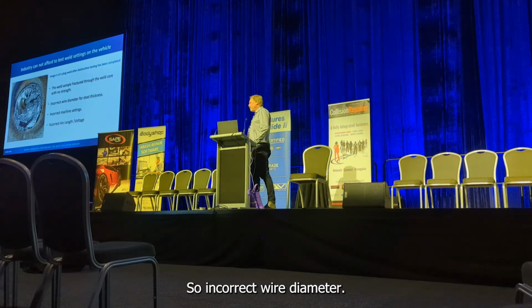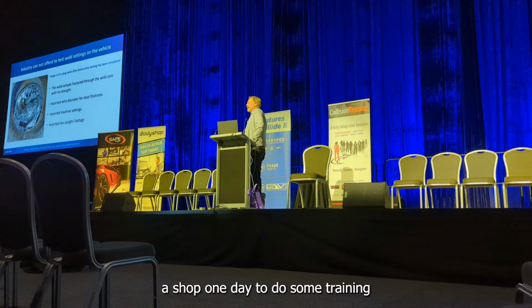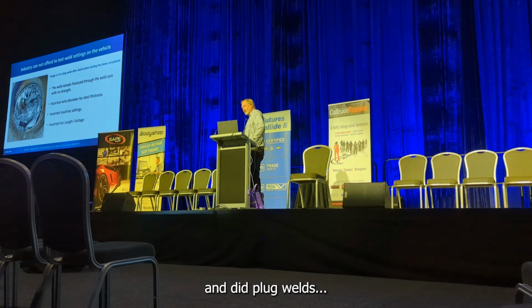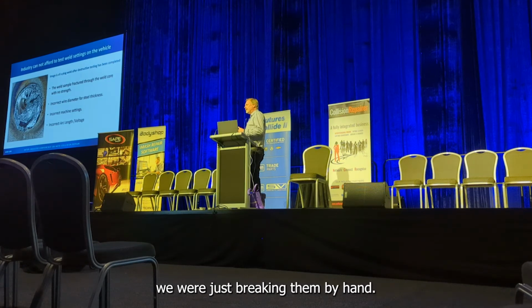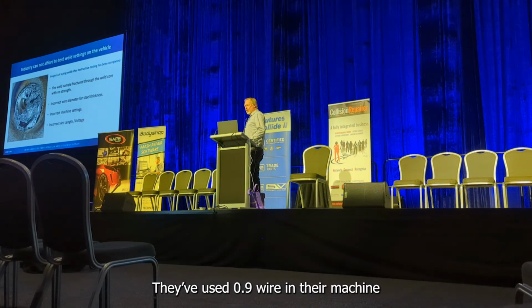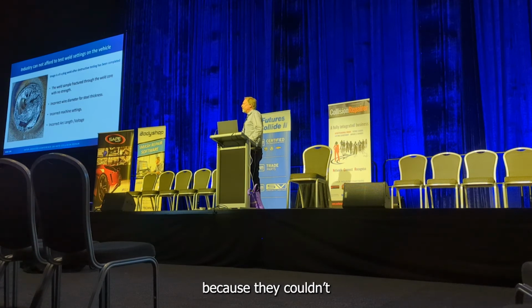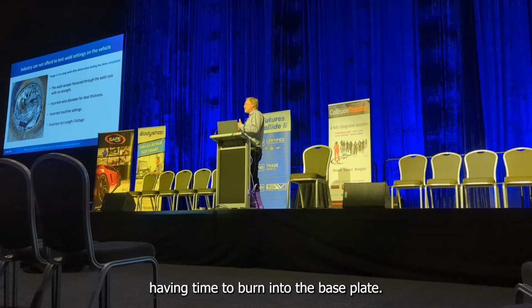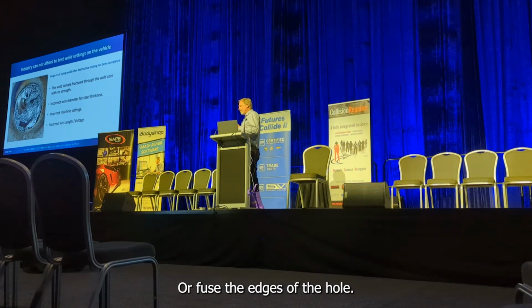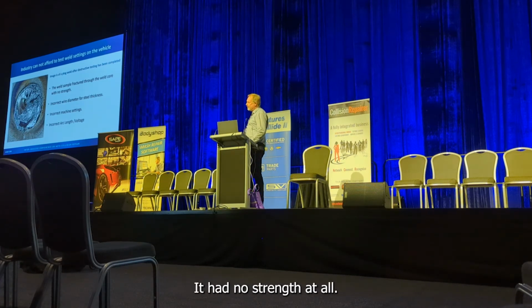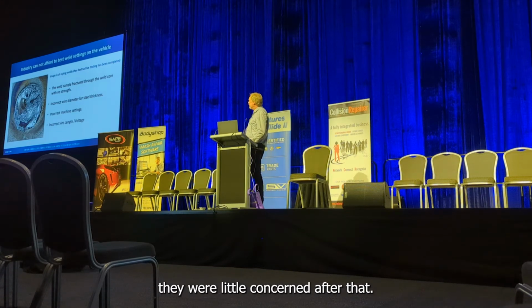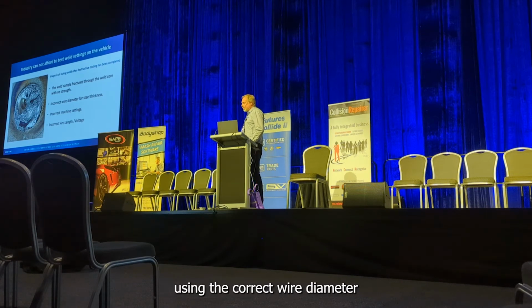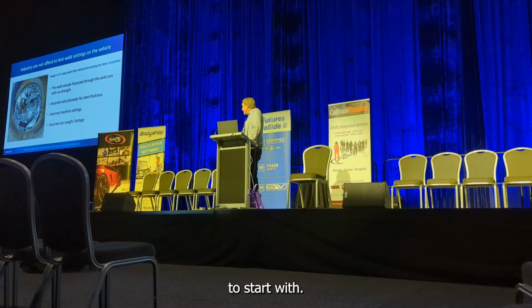So, incorrect wire diameter. I actually went to a shop one day to do some training, and their plug welds, we were just breaking them by hand. They'd used 0.9 wire in their machine for the last 2 years because they couldn't stop the 0.6 or 0.8 wire bird nesting. What was happening, they were filling the plug welds that fast, it wasn't having time to burn into the base plate or fuse the edges of the hole. They had no strength at all. It's a bit of an eye-opener for that shop. They were a little bit concerned after that. So we need to make sure we're using the correct wire diameter to start with.